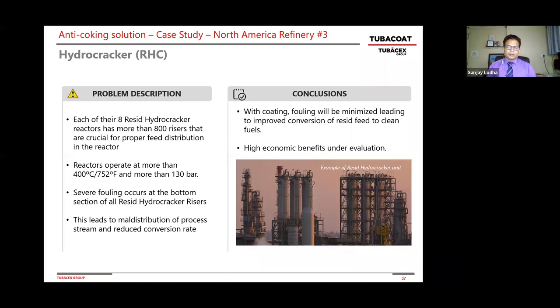And due to the velocity regimes of the hydrocarbons, they have a severe fouling at the bottom section of the hydrocracker risers. And once they have this fouling and cracking, that leads to maldistribution, and they're not getting the conversion they would desire. So with the coating, they will be able to minimize this erosion and fouling, and it is expected to give a far better conversion. Again, this project is for 2021 due to COVID-19, and we'll keep you posted on the benefits that will come out of this trial as well.